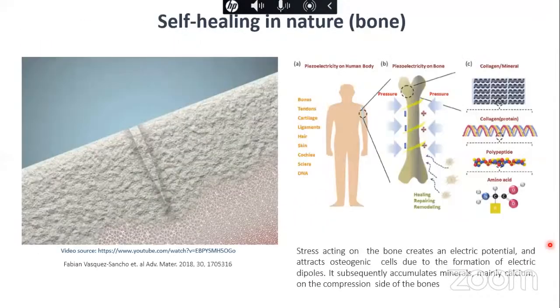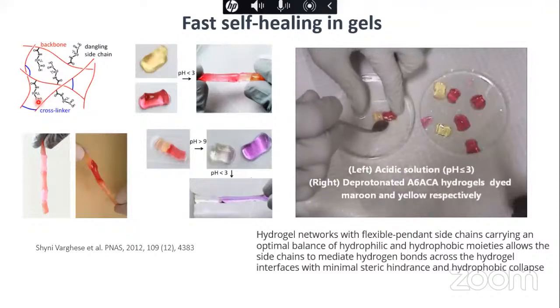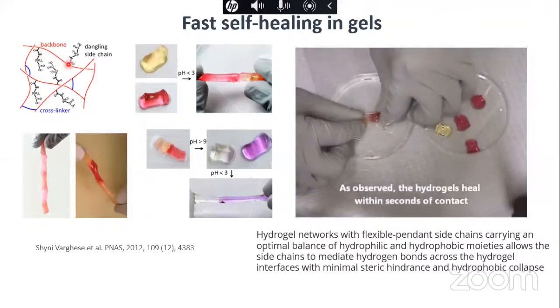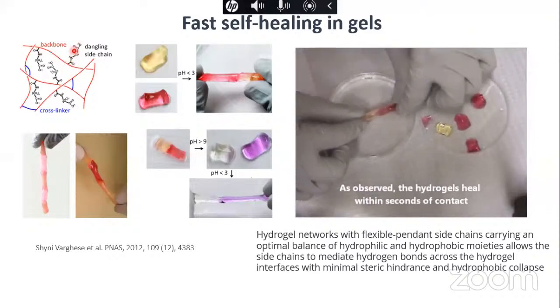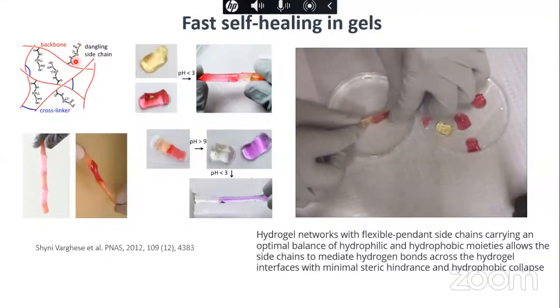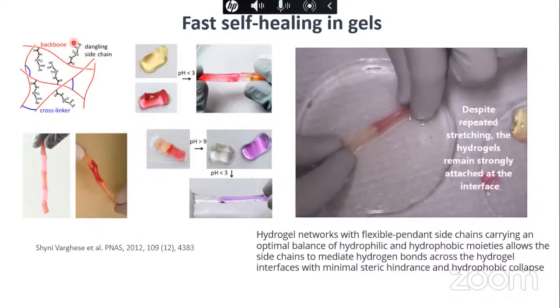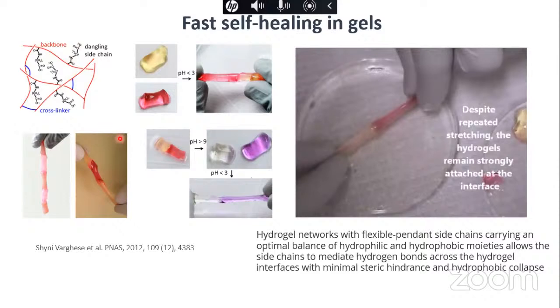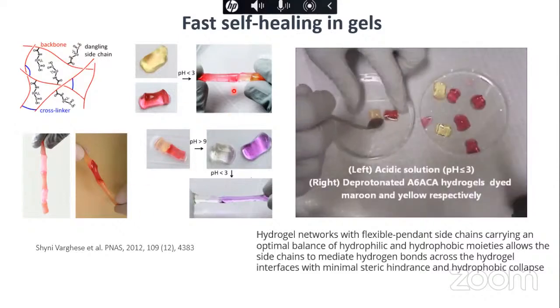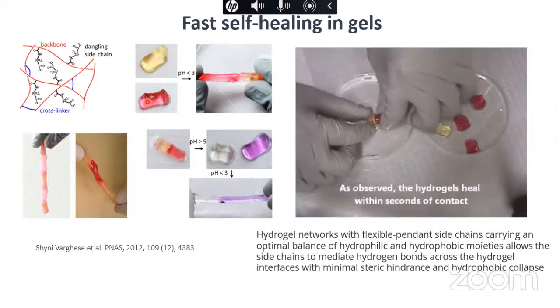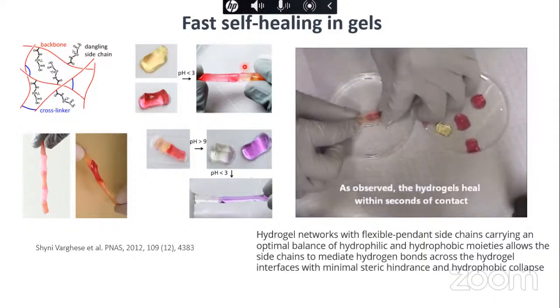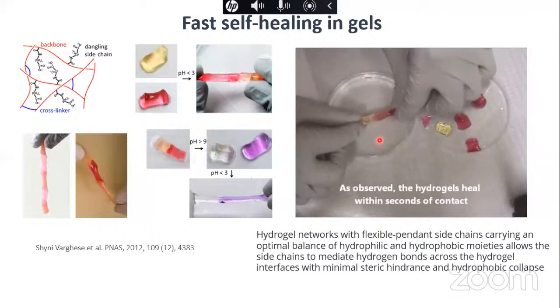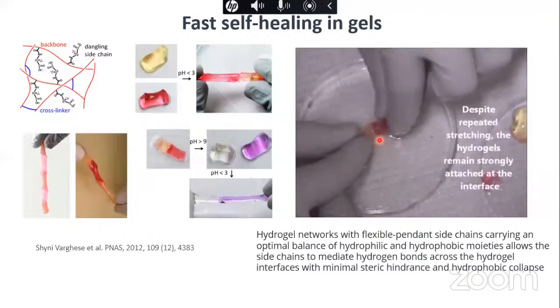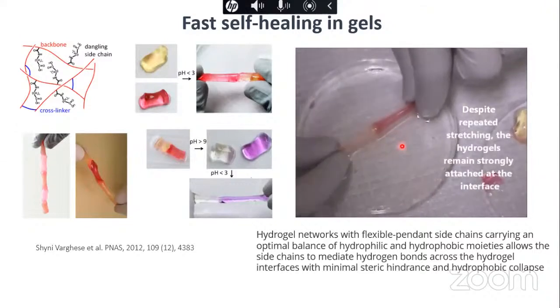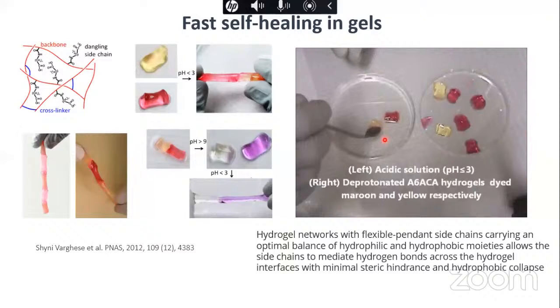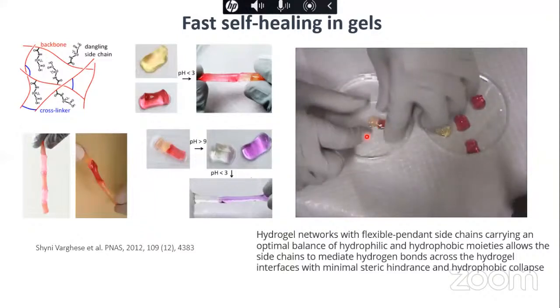For example, this is a gel, where you have a polymer with hydrogen bonding polar groups as side chains. You can see that there are a lot of hydrogen bonding groups, and it forms a nice gel type of material, a very soft gel. Then you take this polymer gel, cut it, and put the pieces together. They nicely heal. If you leave them in a buffer kind of solution and put them together after deforming, they nicely heal, and it is very fast also.